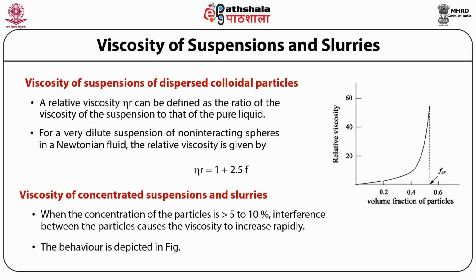For an aqueous suspension of latex spheres of diameter 0.7 micrometer, it was found that K is 2.7, FCR is 0.57 to 0.68 depending on the shear rate. The same expression describes the behavior of slurries which may have particle size distribution ranging from colloidal to coarse particles. So a simple equation can be eta r is (1 minus F) to the power minus K. This equation is used sometimes. In this equation, K is equal to 3 for a continuous distribution of sizes that pack more efficiently. K is equal to 21 for coarse particles of uniform particle size. Now, as 1 minus F is less than 1, eta r is higher for the latter case.